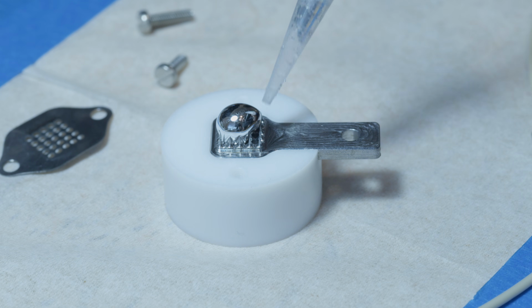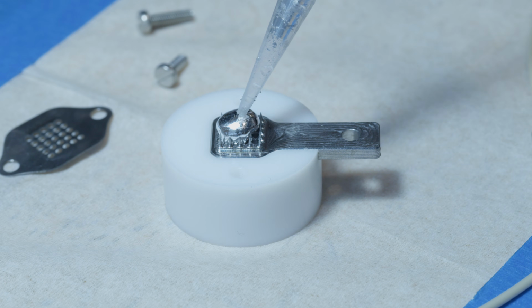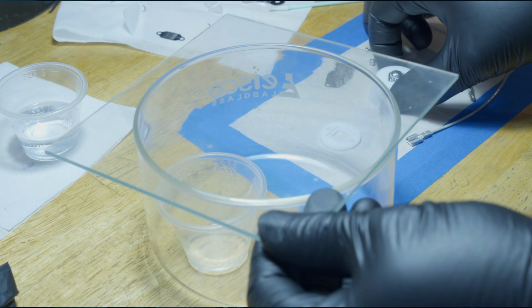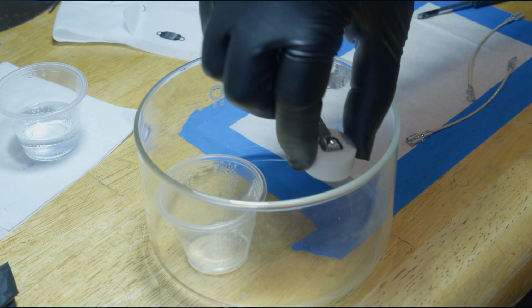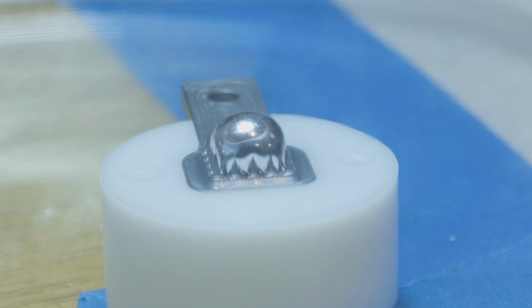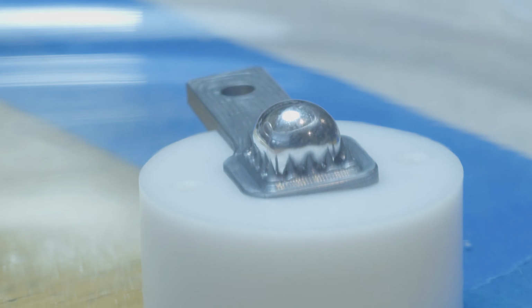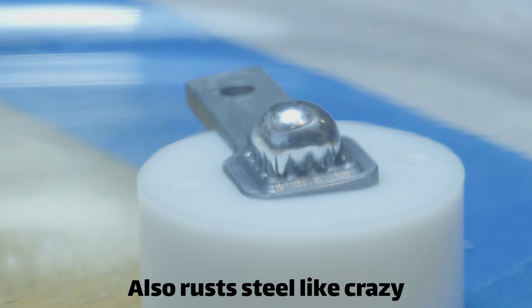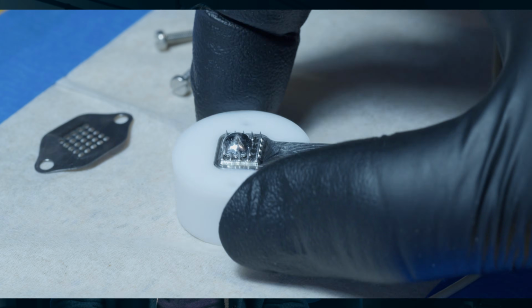Coating with metal is challenging here too, but a little easier than the glass. Galinstan just kind of sucks to work with, honestly. I found the easiest way to coat it is to put it in a chamber with some hydrochloric acid fumes, which helps accelerate the wetting process. The fumes dissolve and help prevent the oxide from reforming on the surface of the galinstan. And this helps the liquid metal wet out other metals a lot easier. With some additional mechanical encouragement, I got most of the spikes covered.